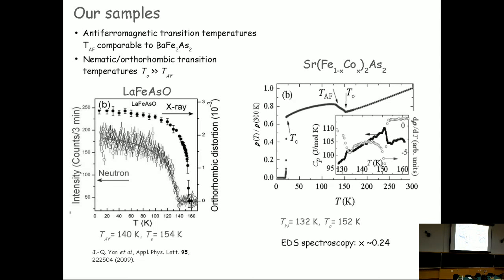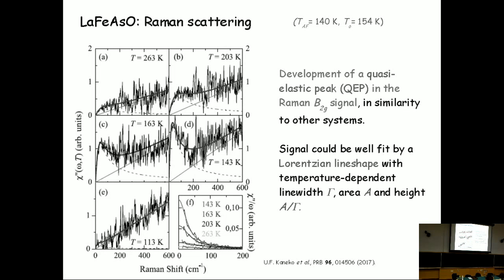You also have in the specific heat the 2 transitions showing up. So there are clearly 2 separate transitions in these samples. And in this case, the difference between the 2 is 20 Kelvin. So X, the doping here, was determined by EDS, energy dispersive spectroscopy, which is 24% doping. And this is what we have here.